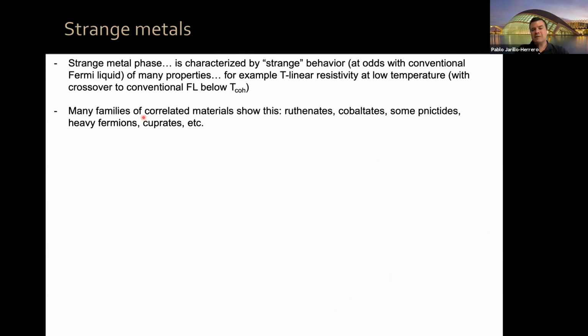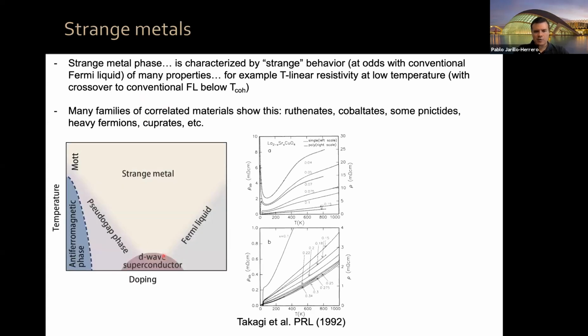Now, this is a behavior that many families of correlated materials show: ruthenates, cobaltates, some pnictides, heavy fermions, cuprates, etc. So in this famous phase diagram of the cuprates, this is this big wedge above the optimal doping in the superconducting dome, in between the pseudogap phase and a more conventional Fermi liquid behavior in the overdoped region. As you can see here in this diagram, this is data from the cuprates as a function of doping, and there's a region of doping for which this behavior is very, very linear right there.